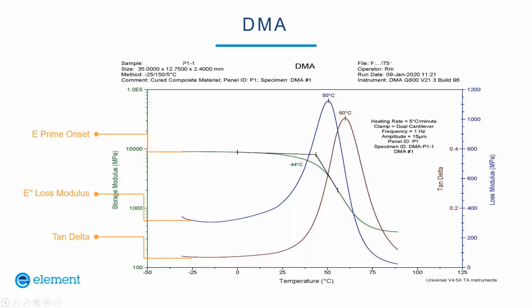Now the E double prime or loss modulus is this blue line, and you can see it goes up to a sharp peak. And it's very easy to determine where the peak is and get a glass transition temperature there. It's a little bit higher, 50 degrees C. Similarly, tan delta, that's the difference in the tangent angle of the force and deflection curves, is also easily discernible, and it's 60 degrees C.